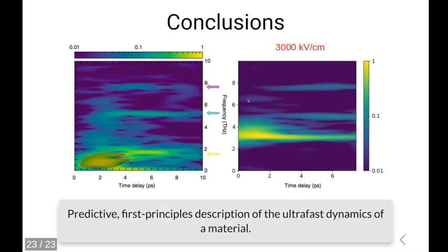We have other results, which I've not shown, in which we actually obtain the same frequency as the experiment by straining. If you take a GGA strontium titanate, you do a simple strain, you can find a strain at which you can almost match exactly the experimental spectrum, and indeed the results don't change very much. We still observe the same phonon upconversion; it changes quantitatively. Indeed, the exact energy that is transferred is different, but not so much.